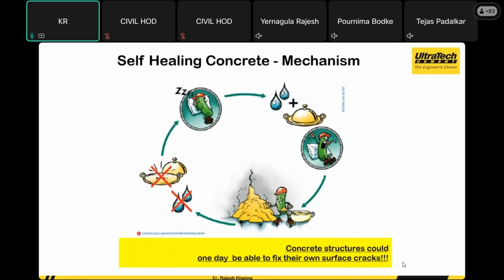This is how to make you understand. There is a pictorial to make you understand: if there is any water or moisture presence, it gets activated and the healing process happens. It doesn't happen overnight. It takes about 50 days, 60 days, or even 100 days to heal the size of the crack that you can see.